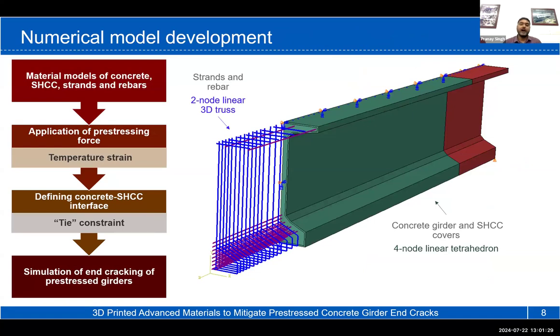For understanding the hardened property objectives that we will need, particularly the strain hardening capacity of these materials, we developed a numerical model. So this is a 3-dimensional nonlinear finite element model, and we actually model a girder which was experimentally tested at University of Texas, and they got very wide cracks. So they had significant cracks at the end, and that's why it represents one of the worst cases of end zone cracking. So we modeled the same girder with the conventional concrete, and then modified it with SHCC at the ends.